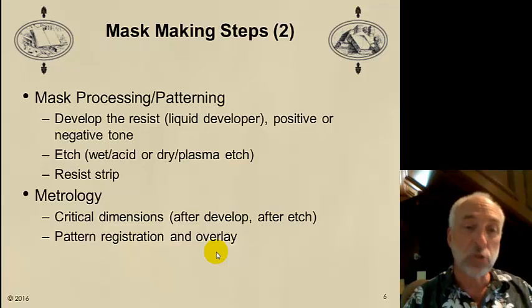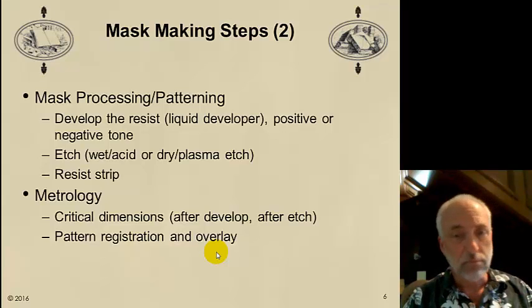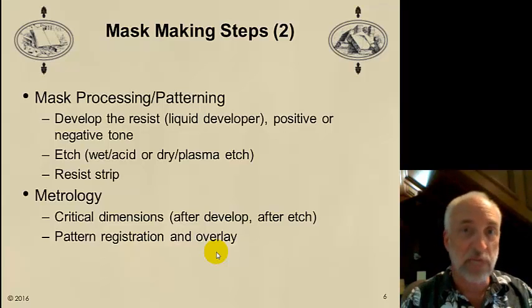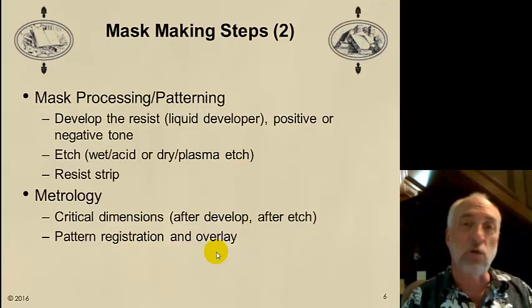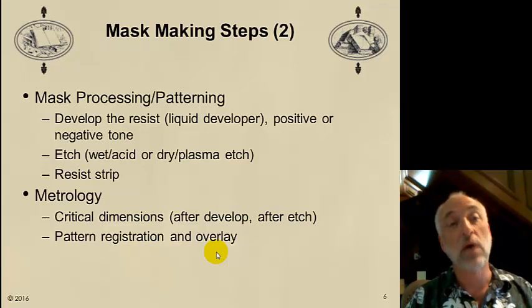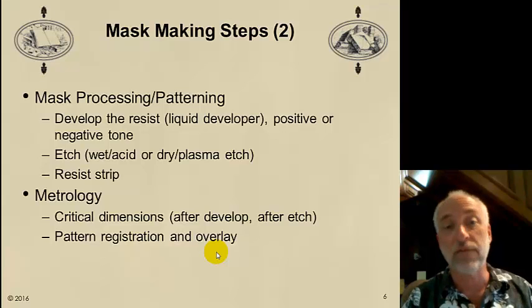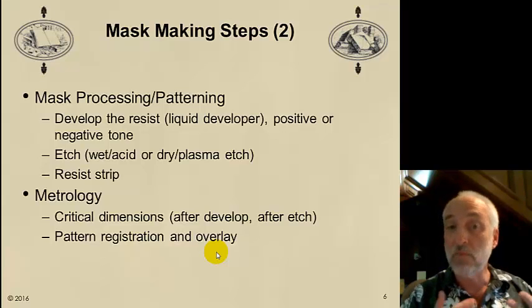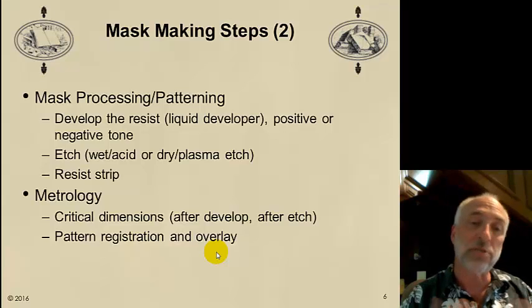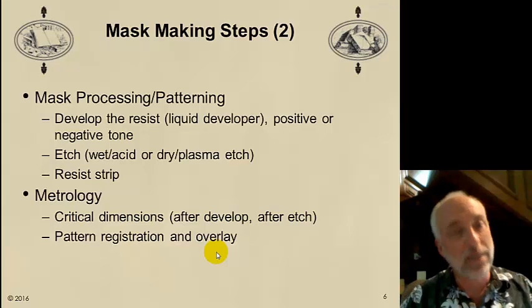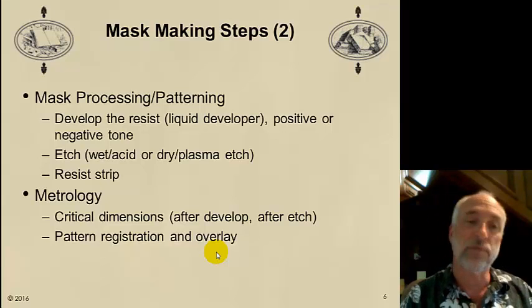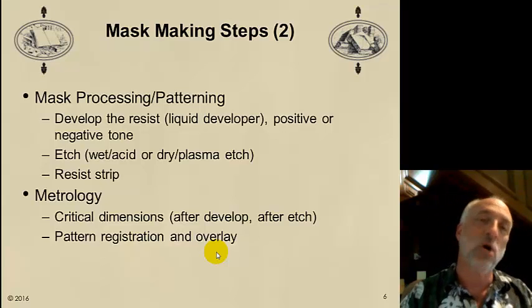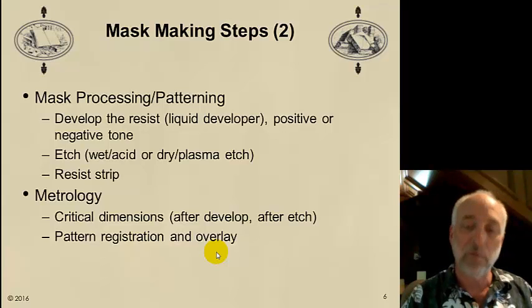The main two things we look at are the critical dimensions, to make sure they're the proper size and within specifications, and the registration and overlay of the patterns. These are the same things we look at when we're printing wafers after a lithography step, but the same errors in the critical dimensions or overlay or registration of the photomask will have a direct impact on those same errors on the wafer. So we've got to get it right in the mask first, or we have no hope of getting it right when we print wafers with them.